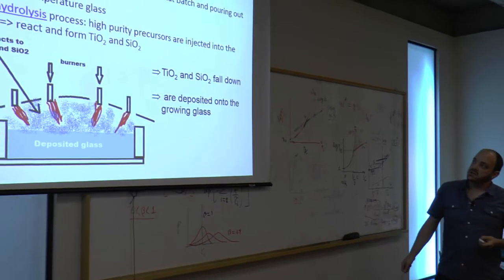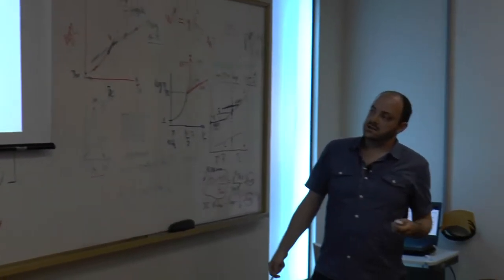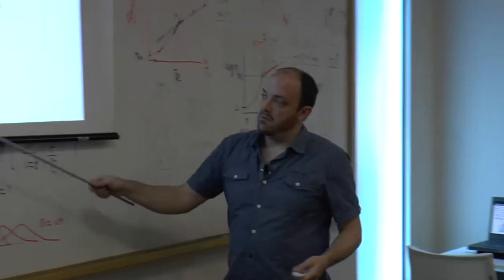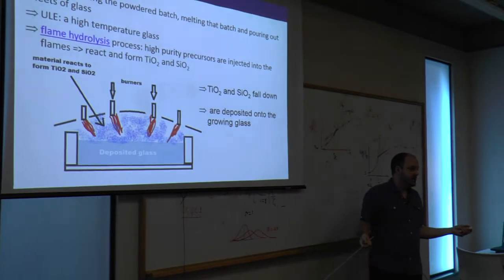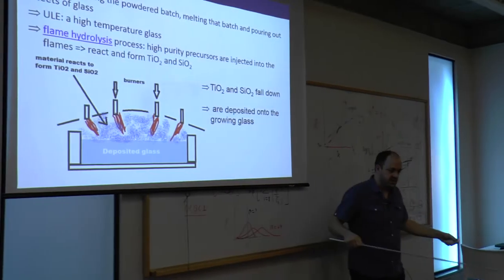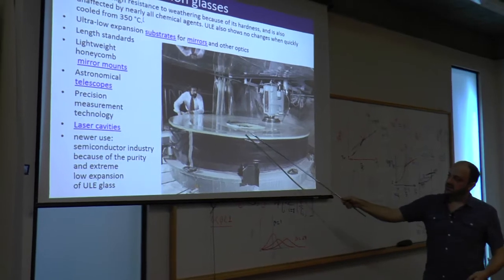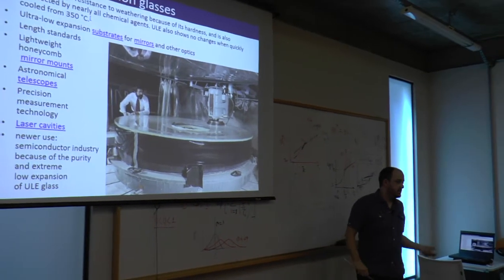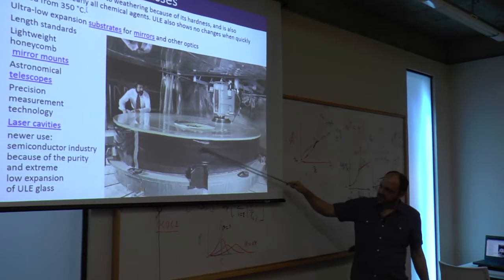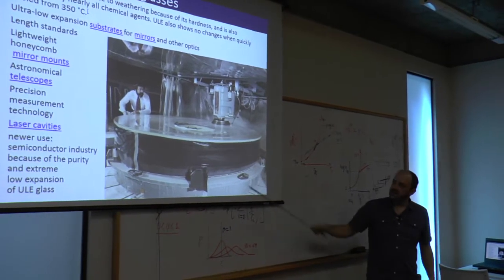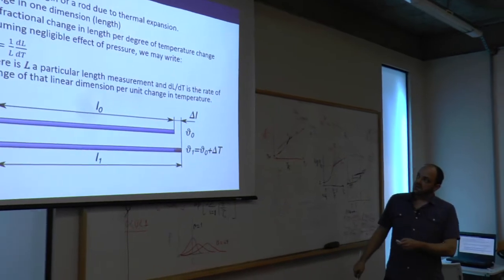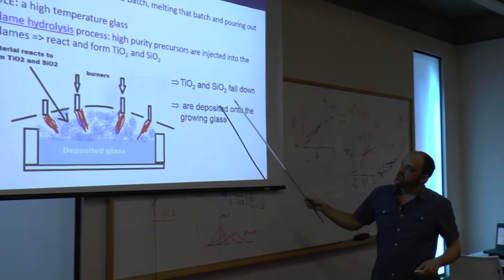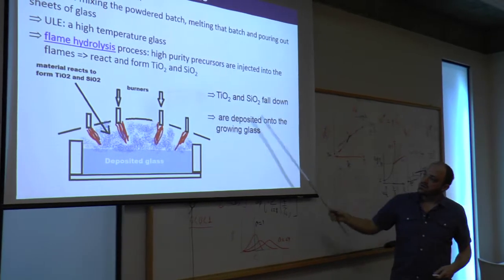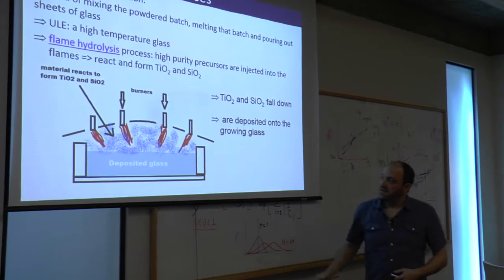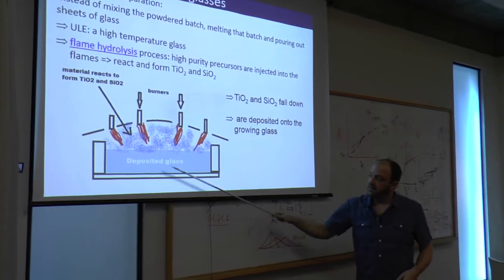They have a kind of an interesting preparation for the glass. It's very difficult to make a glass that's big enough for an astronomical mirror. What would happen if you had a huge volume glass the size of this table? You saw the picture here. It's the size of a guy. What would happen to a glass this big if you made it with conventional methods? You would have all kinds of strains and stresses from the surface cooling to the inside. So they have to make these glasses in a completely different way. And they actually inject a small amount of titanium with silica into these burners, and the gas is deposited layer by layer on the glass below. So quite a different preparation.